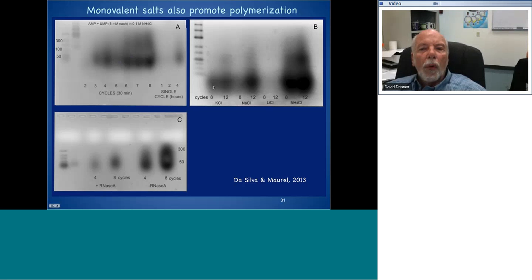Now here are 4 different salts. It's very important. Potassium chloride, sodium chloride, lithium chloride, ammonium chloride. No lipid now. Only these salts in about a 10 to 1 ratio with respect to the monomers present. So you can see 8 cycles and 12 cycles with KCl, 8 and 12 with sodium chloride. Look at this. Lithium chloride does not promote the reaction. We think the reason is that lithium is a highly hydrated cation, and it brings down so much water, even as it dries down, that the condensation reaction cannot occur with the lithium chloride.